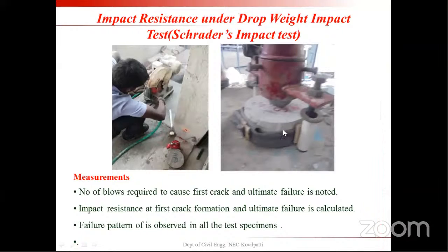And then a hammer blow is allowed on this disc specimen, and the number of blows is counted to cause the first crack and ultimate failure. So this is the observation we have to take. Based on the blows, we can convert it to the energy absorbed by the specimens. Ultimate failure and first crack observations, and failure pattern are also noted. And this table shows the impact resistance, the energy absorption capacity under impact load.